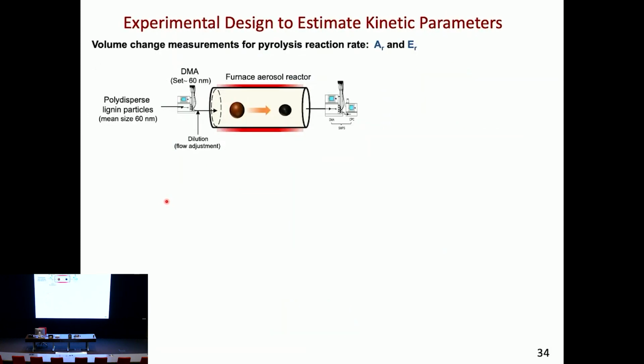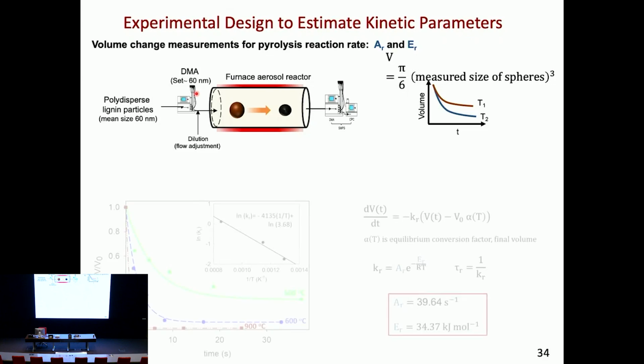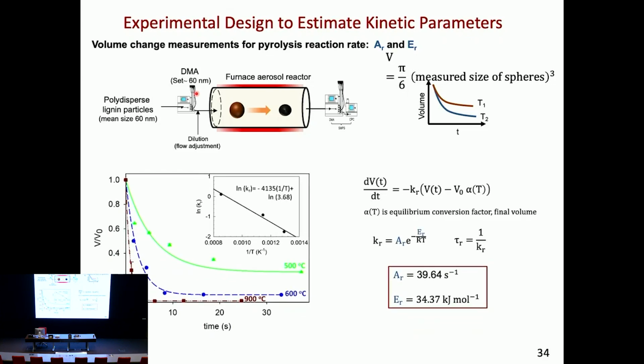So I go back, I do very controlled experiments. Now, see how I'm using my tools. This is just the schematic of a differential mobility analyzer. I put it at the inlet so that I can take a single size, monodispersed size into my reactor. I don't want to play with that distribution. I can change the size. So at the inlet, I get a single size in, and then I measure at the outlet what happened to that single size, right? So this then allows me to, of course, look at the change in the size or the volume, and I plot out and get an Arrhenius type expression and can fit the reaction rate constant and so forth.